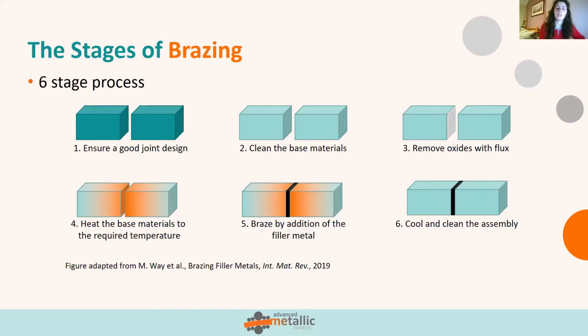You then heat the base materials up to the required temperature for the brazing, and then introduce the filler metal, which typically spreads through the joint via capillary action. Then the entire assembly is cooled and cleaned of any excess flux and such like.